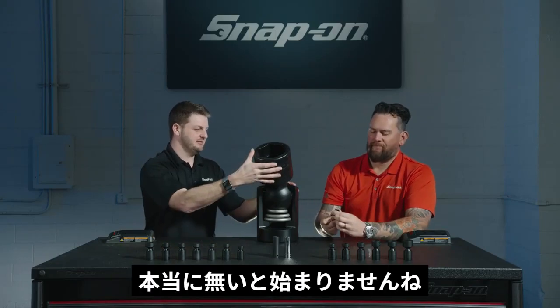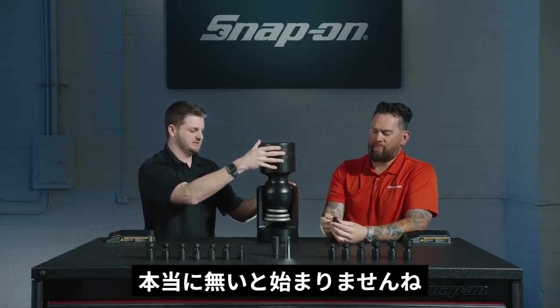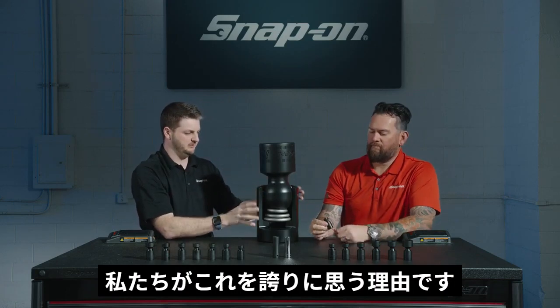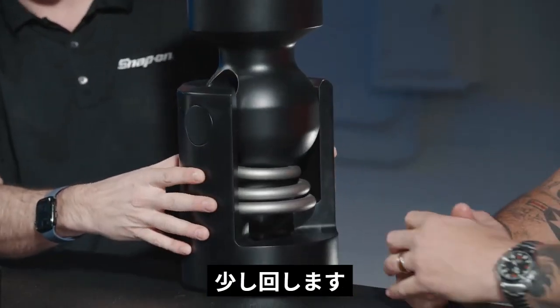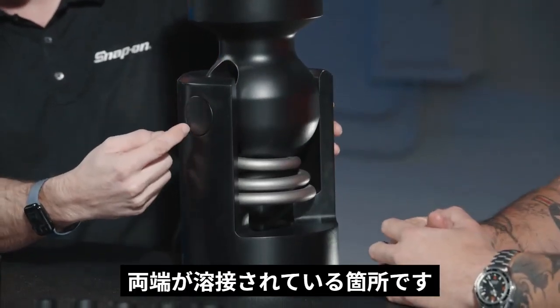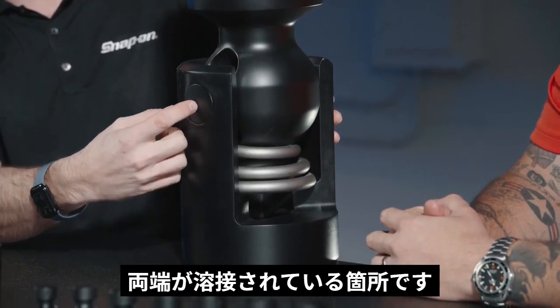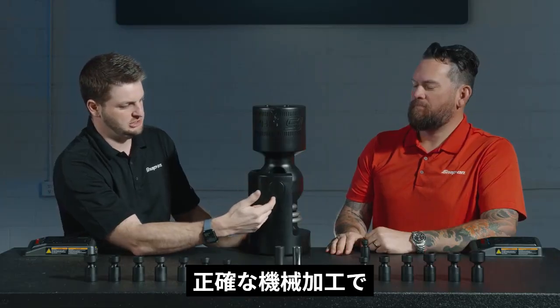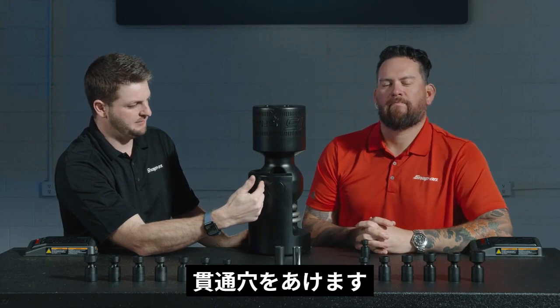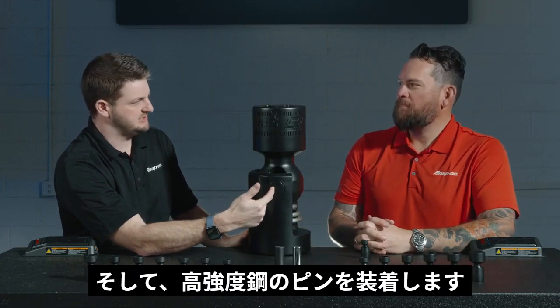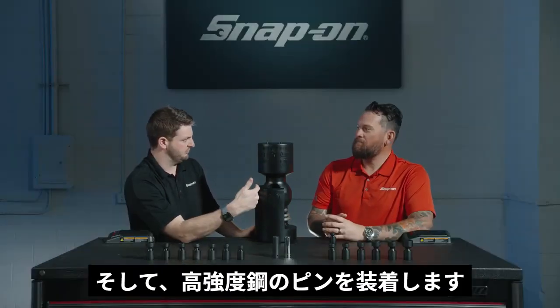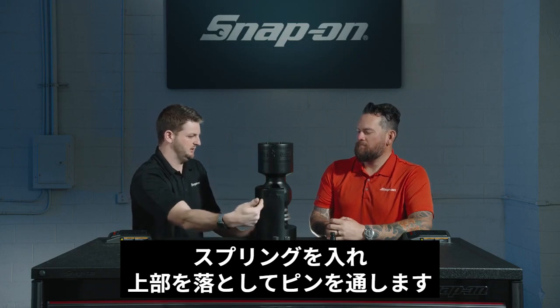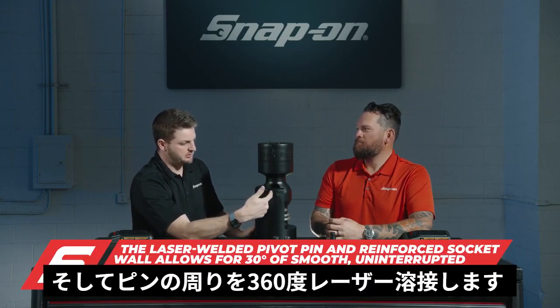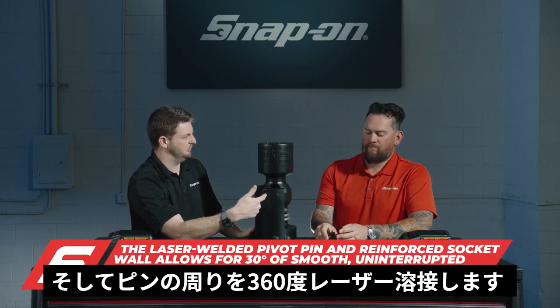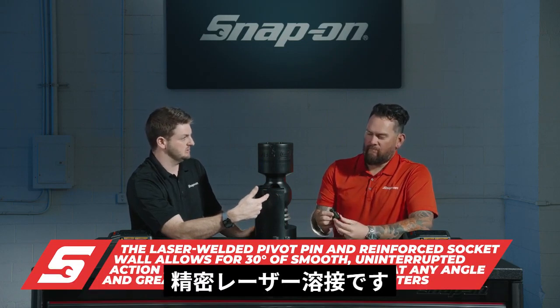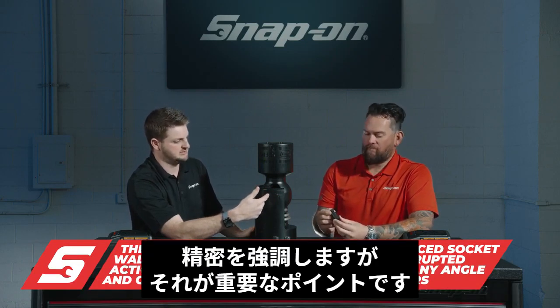Exactly. Another thing that really is the bread and butter of a socket and why we are so proud of this, I'll just rotate this here a little bit, is where the two ends are permanently joined together. Okay, so we precision machine a hole through the drive end. We then take a high strength steel pin, put that through, right? So you drop the top, you got the spring in there, run the pin through, and then we 360-degree laser weld this. This is a precision laser weld, and I talk about the precision because that's important.